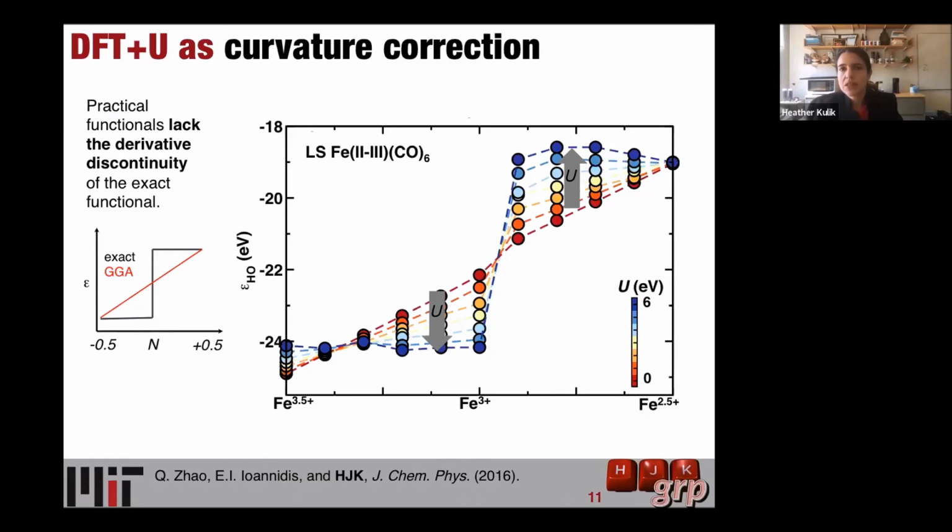And usually this is where you can run into trouble, because if you need to use a U of say 20 eV to recover your band gap, then you're also going to do the things that some of the earlier questions alluded to, which is like maybe you'll mess up the lattice parameter, maybe you'll get another property wrong. So if you need a really large U to increase the band gap, you probably don't want to use DFT+U to recover the band gap.